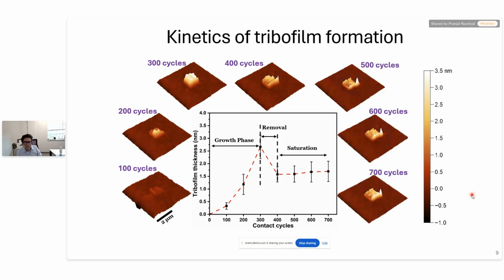tribofilm thickness. So we think this behavior is because in the beginning, the catalytic sites are available. So the hydrocarbons from the air come and adsorb on the surface, and they undergo mechanochemical reaction because of the sliding AFM tip. Once those catalytic sites are exhausted, the growth of tribofilm stops and we reach a steady state or saturated state.